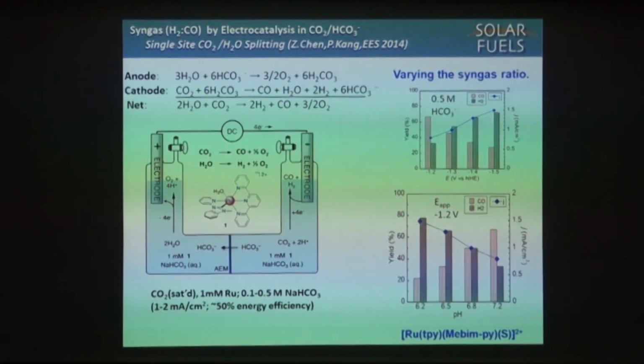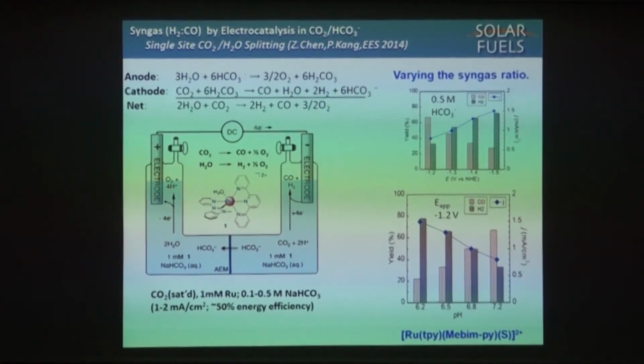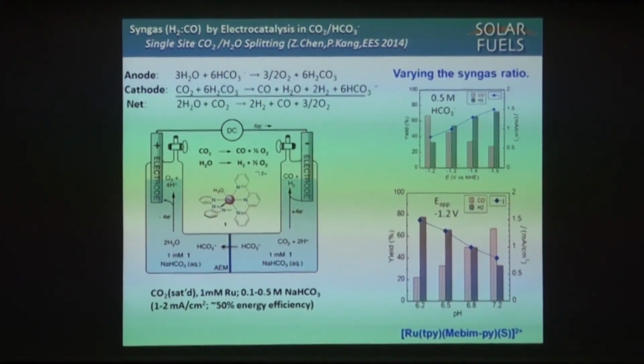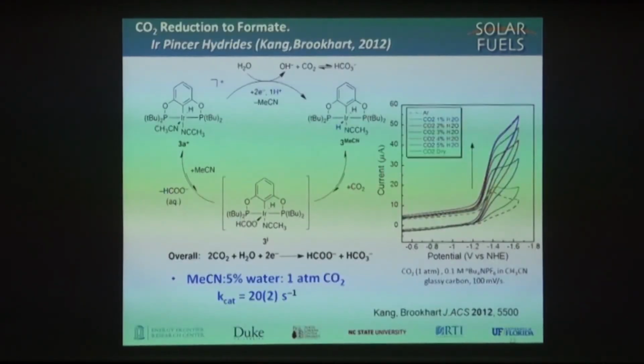And not only that, you can control the relative amounts. It turns out syngas in different ratios is used to make different products. If you have a fixed potential and increase the bicarbonate concentration in the CO2 bicarbonate mix, you can control the ratio that way. Or you can change the potential and dictate the products. If you look at this cell, the way it operates: 1 millimolar complex, 1 to 2 milliamps per centimeter squared, 50% energy efficiency. We're in the process now of scaling this up using flow-through reactors. I think there's a chance this would become of interest economically.